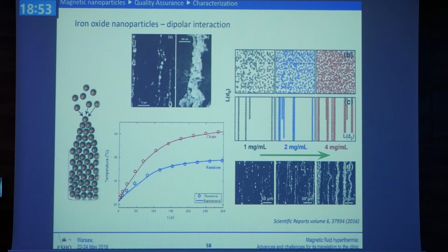And of course, you can increase the anisotropy if you make the nanoparticles build chains, then you have high anisotropy. And then this is from a publication of our group. You can show here that if the nanoparticles are randomly oriented, compared to when they are chained, they form anisotropic structures, you can have a higher temperature rise because the SLP of these nanoparticles is higher.